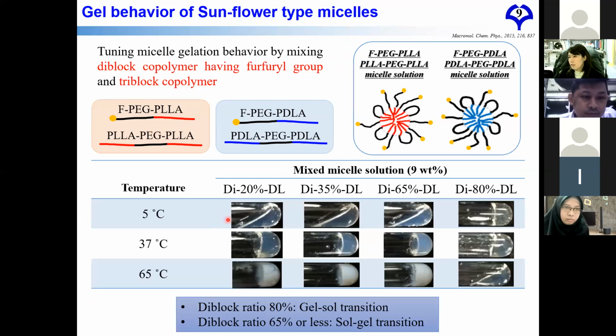Because we want to have the Diels-Alder reaction in the hydrophilic segment, first we synthesize the furan group at the PEG end to obtain the diblock copolymers. So you can see here, this is the F-PEG-PLLA and PLLA-PEG-PLLA micelle solution. So we can obtain this kind of sunflower type micelle solution.